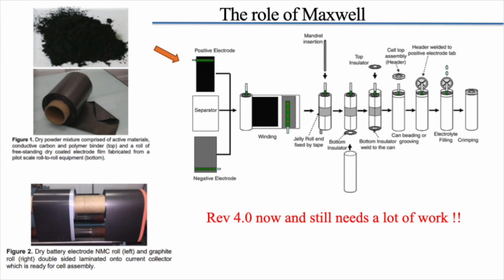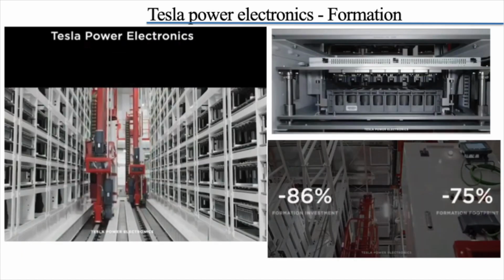So combined with the tabless design and DBE, we can expect significant improvement in the power density and energy density. Now, this is common, the bottom insulator, the bottom cap, top cap. This part is common whether it is 2170 or 4680. But another interesting thing is they mentioned the formation. They were able to reduce the formation cost, equipment cost by 86% and the footprint by 75%.